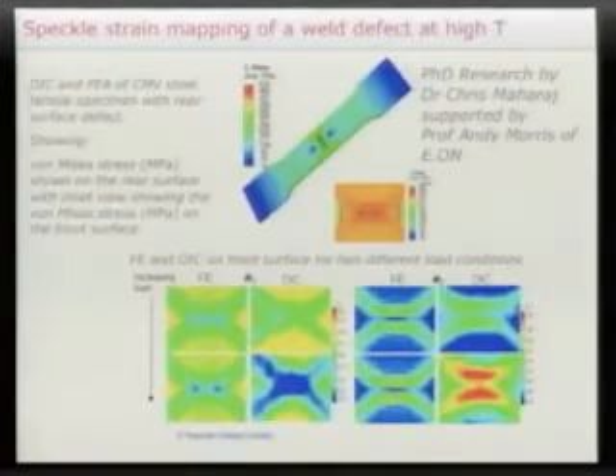We're also interested in optical techniques for measuring strain, like the ARAMIS system, which is effectively you put little pips on the surface and track the silicon nitride or ceramic pips. And we're also interested in developing and applying the high-temperature coatings type of technology, which is the strain visualization type of system. So this is putting a speckle pattern using high temperature paints which stays in place, and then you track, particularly over a weld, because welds are obviously key sites where you want to put this strain visualization technique into place.